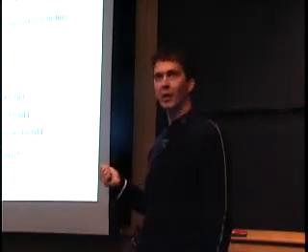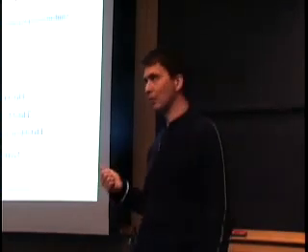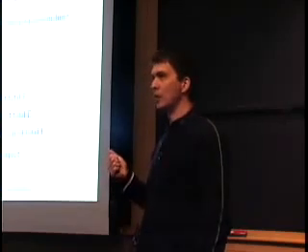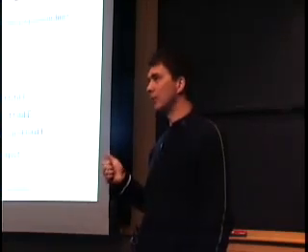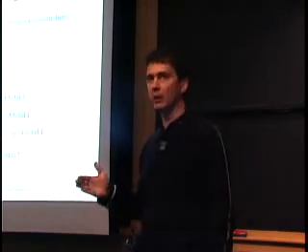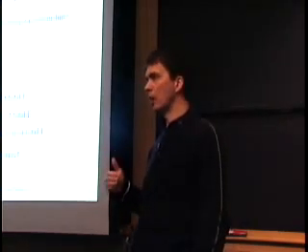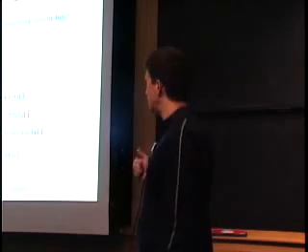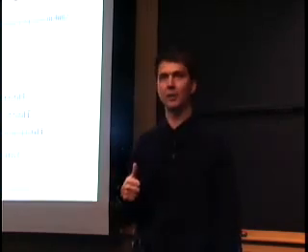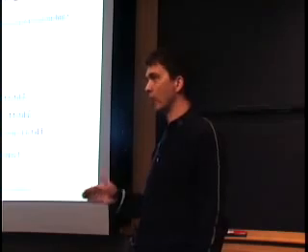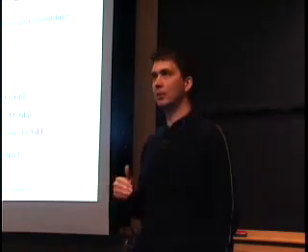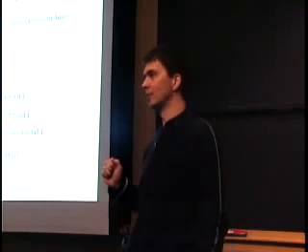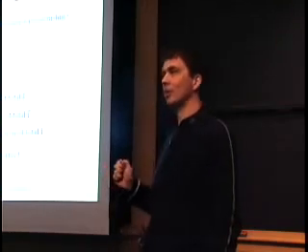The only reason we're here and we can get physical behavior right is because a lot of the error that density functional theory makes in LDA and GGA is systematic. And so a lot of it cancels away when you take energy differences. When I do FCC and BCC vanadium, yes, I may have an error of 10 to the minus 4 in the energy, but most of it cancels away when I take the energy differences. And that's why we're lucky.